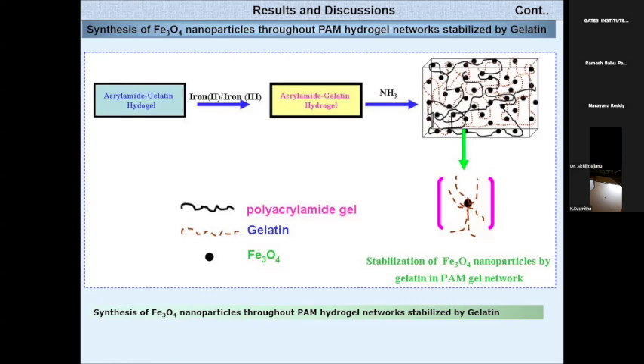After obtaining the polymer, we put this polymer into the iron ion solution. On one side we have developed acrylamide hydrogels with gelatin. Simultaneously, you have to take a certain concentration of iron hexahydrate, iron hexachloride solution, dissolved into solution. You have to prepare that solution. Then you take this acrylamide hydrogel and keep it in the iron ion solution overnight, so like you can say 24 hours.